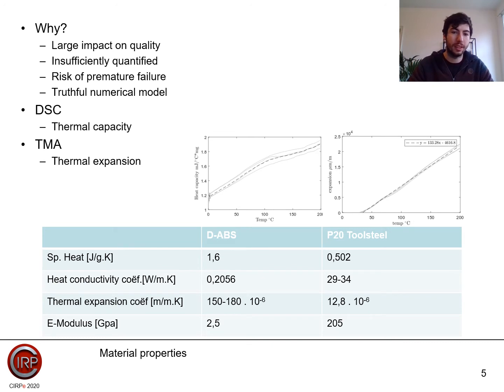First of all, material tests. Why did we do this? Several thermo-mechanical material parameters that have a large impact on the quality of an injection molding mold produced in digital ABS, and hence the performance of the injection molding process, are insufficiently quantified. The rather high thermal expansion coefficient, the low thermal conductivity, and the low glass transition temperature of the digital ABS cause risks of premature failure due to the thermal load induced by the injected polymer melt. Therefore, establishing these parameters is a fundamental prerequisite to obtain a robust production process, as well as developing truthful numerical models.